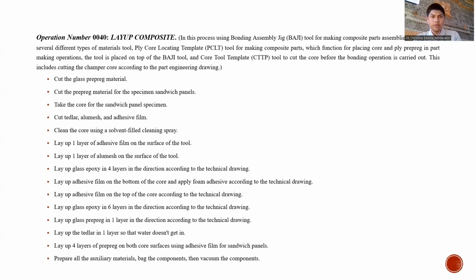Okay, these are the following steps in the operation number 0040. Cut the glass prepreg material, then cut the prepreg materials for the specimen sandwich panel, and then take the core for the sandwich panel specimen, then cut Tedlar alumesh and adhesive film, then clean the core using a solvent-filled cleaning spray, then lay up one layer of adhesive film on the surface of the tool, and then lay up one layer of alumesh on the surface of the tool, and then lay up glass epoxy in 4 layers in the direction according to the technical drawing, and then lay up adhesive film on the bottom of the core and apply foam adhesive according to the technical drawing.